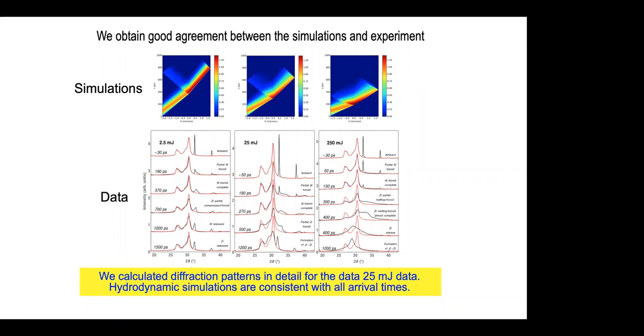And in fact, one of the issues with interpreting this data is the fact that, well, number one, we have basically non-steady waves going into the material, and you can actually see this in the simulation somewhat here. So at these higher pressures, the wave speeds are a little bit higher than they are at lower pressures at the shock front in this, and so the wave is actually evolving as it goes through the ablator.